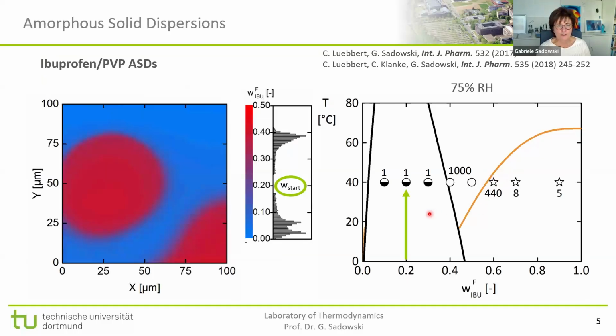Then what we usually do is use confocal Raman spectroscopy. That means we scan the samples in steps. What you see here, the total length is 100 times 100 microns, and we can make scans in steps of 2 microns in the 2 directions. The content of the ibuprofen is color-coded. Red means high content of Ibu, and blue means low content of Ibu, that means polymer in this case.